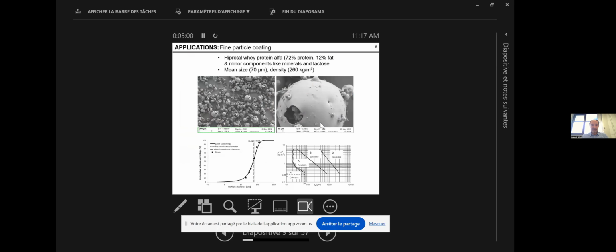So anyway, we use that principle again for coating fine particles. The problem with fine particles is that you need to work with thin slots, because you need to inject an awful lot of momentum for given gas flow rate. So you can play with the momentum injected versus gas flow rate injected by just decreasing the slot size or the number of slots. You inject the same gas at higher velocity, and that allows you a higher momentum, and that keeps the ultrafine particles inside. The price that you pay is pressure drop, but there is something that you have to do in order to treat such fine powders. Yeah?